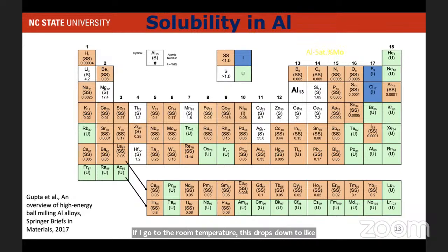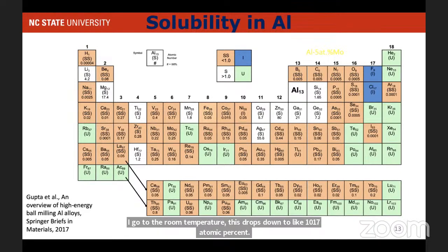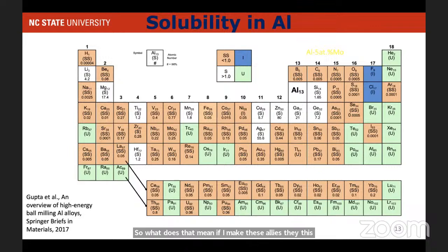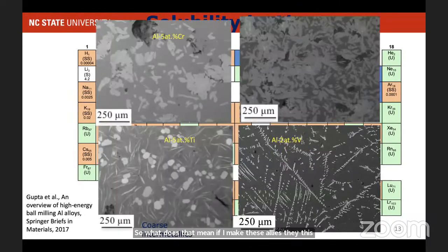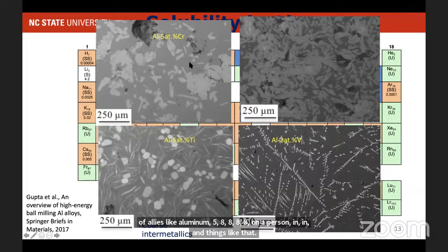So what does that mean? If I make these alloys, these elements won't stay in the solid solution. They make some sort of precipitate. So just for demonstration purposes, we made a bunch of alloys like aluminum 5 atomic percent, chromium, titanium, and things like that. What you see is the matrix, the gray thing, and little brighter intermetallics, which are really big intermetallics. If I make these alloys by casting, all this matrix would be cored, so they're not going to be very useful.